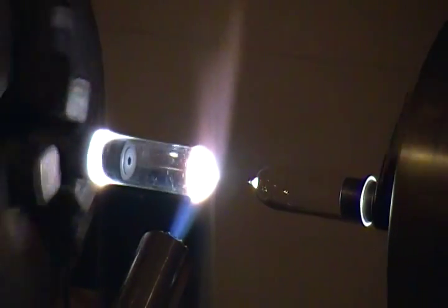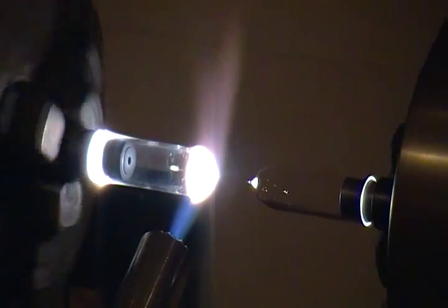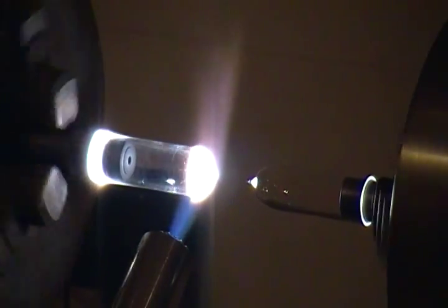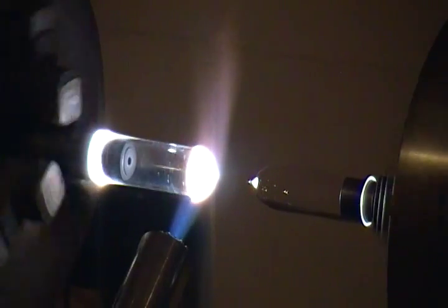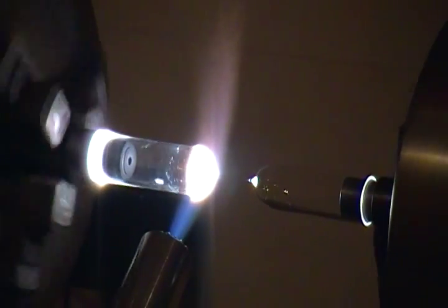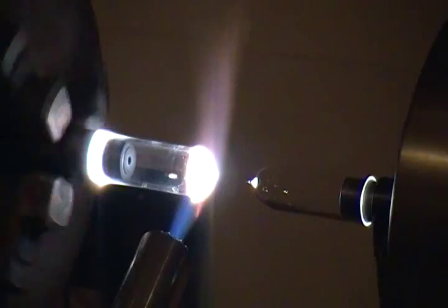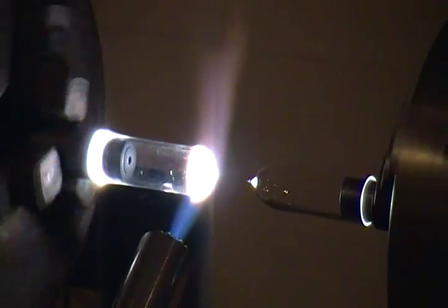You want to avoid bloom, so you have to use the right amount of heat. You don't want to use too hot of a flame and over temp your quartz material and start vaporizing it. Then you get this vaporized silica that deposits outside of the heat of the flame down the colder spots of the glass and it just starts to become a problem.